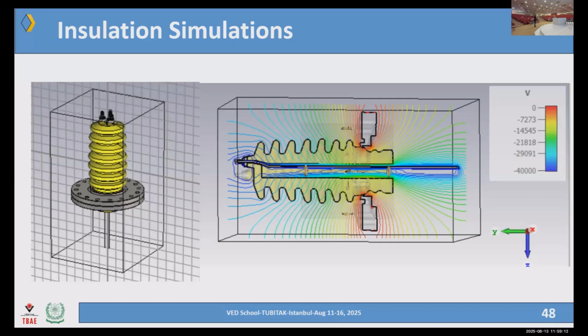We used CST to check if this will withstand the high voltage levels, for high duty cycles even. But this is for DC simulation. What we do is we apply 10% or 20% higher voltages than operation conditions, and we check the potential lines generated by the electrostatic solvers.